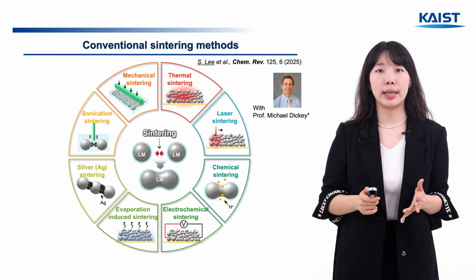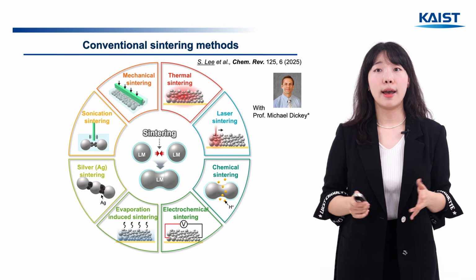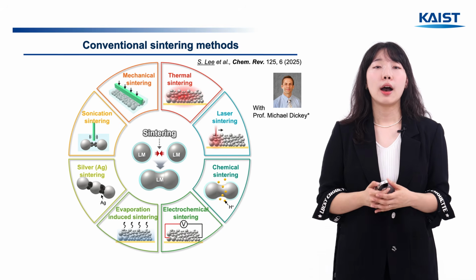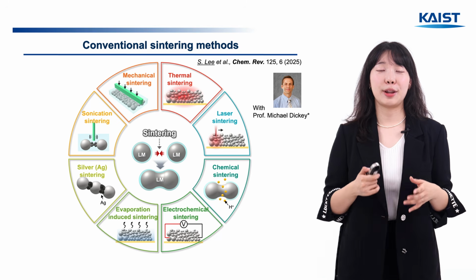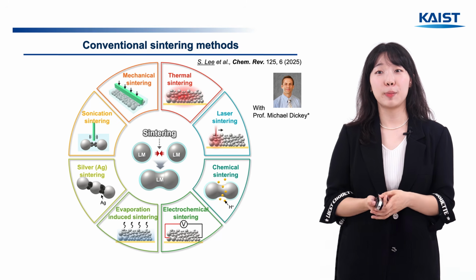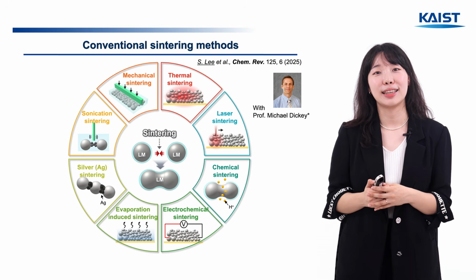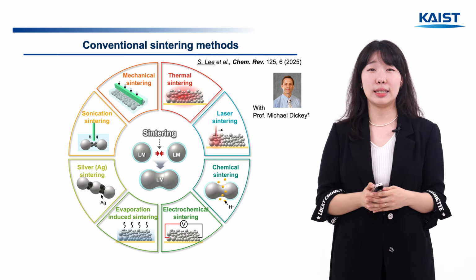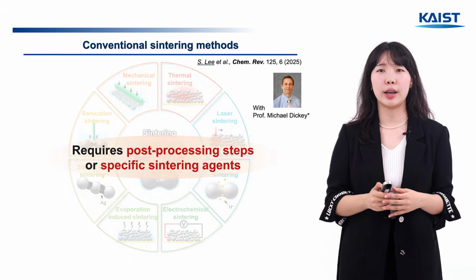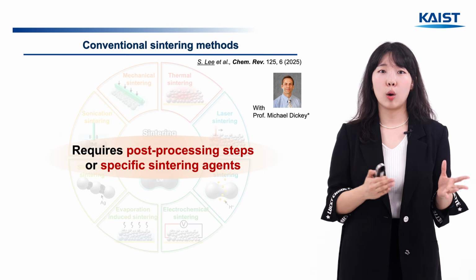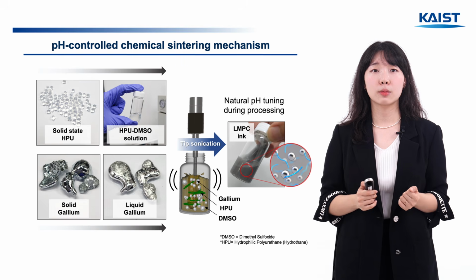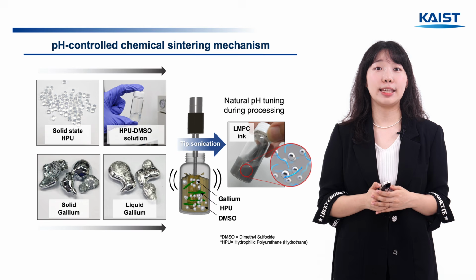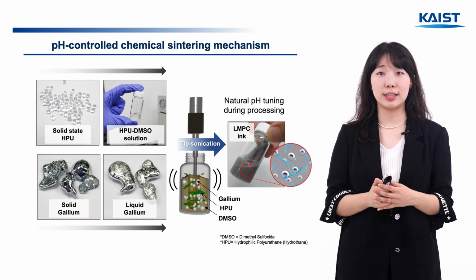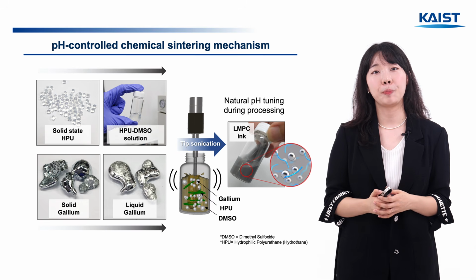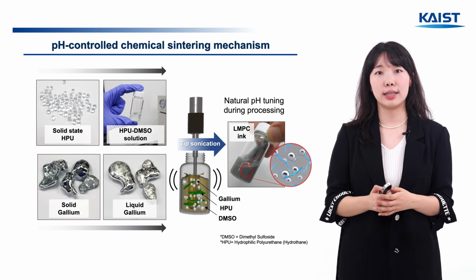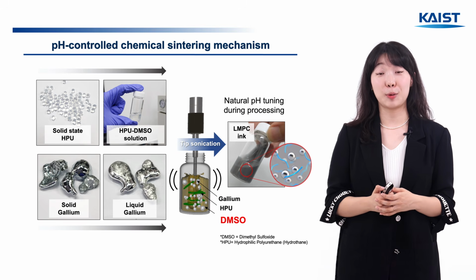Sintering research for making liquid metal particles conductive has been very active. I recently reviewed these various approaches in a Chemical Reviews paper together with Professor Michael Dickey. But the problem is that most existing methods require either a post-processing step or a special sintering agent. So to achieve this, I developed an ink whose pH changes naturally during the process. The key to pH control is the dimethyl sulfoxide, or DMSO.